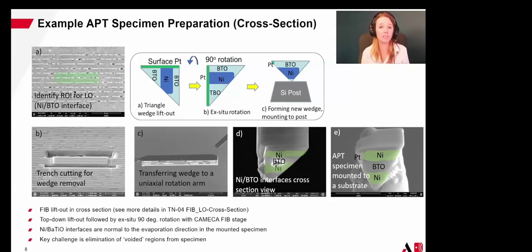Now, a lot of times we know that interesting things are happening at interfaces. So in this case, we wanted to sample or have in our final tip the interface between our metal electrodes and our ceramic material. Now, to do this most effectively, we've chosen to prepare that sample in cross-section. And this is detailed in our technical note 04 if you're not familiar with the process.